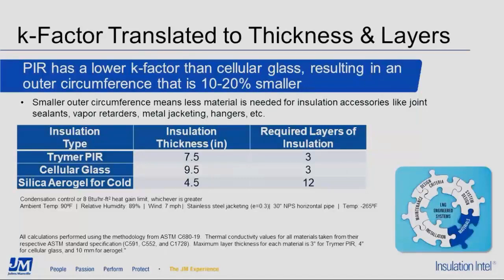Now let's take a look at the total insulation thickness and number of insulation layers required for PIR, cellular glass, and let's include a relative newcomer to the LNG pipe insulation party, silica aerogel. For the reasonable climatic scenario described in the table, you can see the insulation thicknesses required for each material. The greatest thickness required is for cellular glass, while the very low K factor of aerogel yields the lowest thickness. However, total thickness is not the whole story. Look at the last column, which shows the number of layers that must be installed for each material.